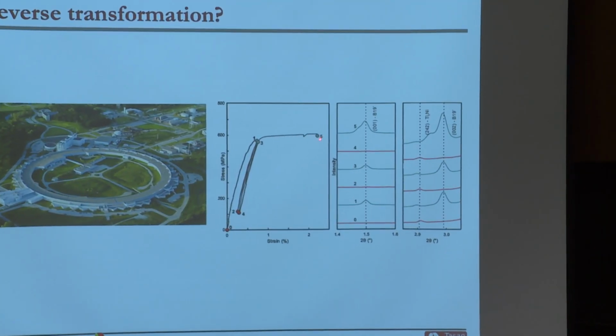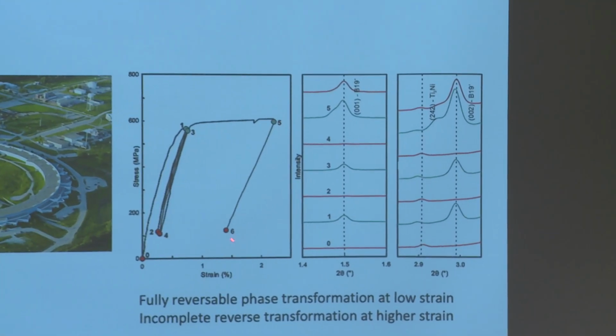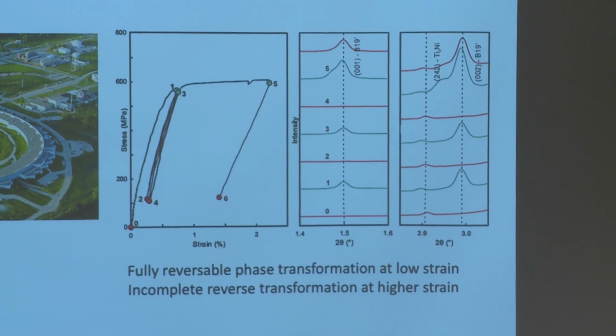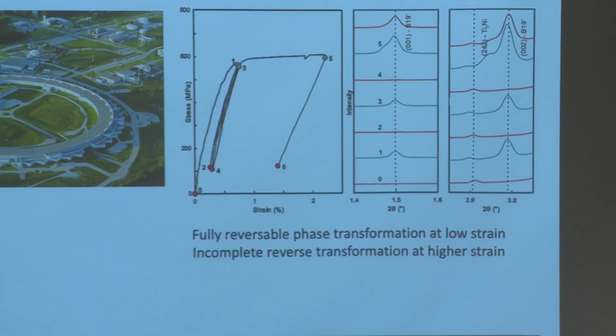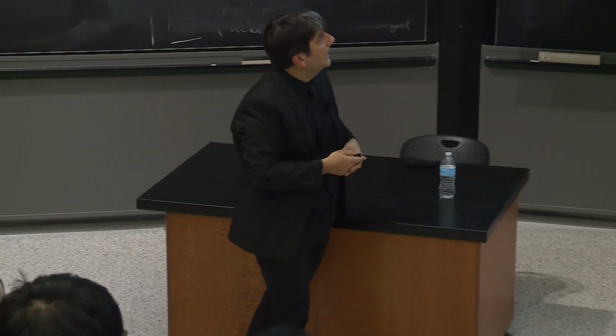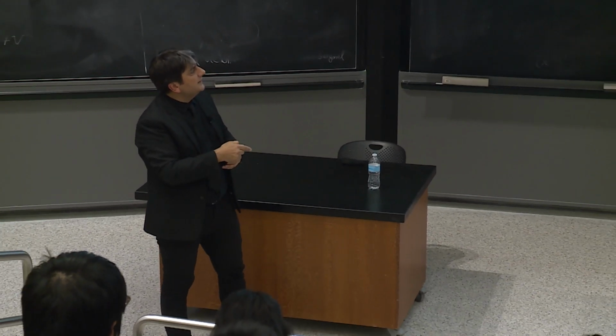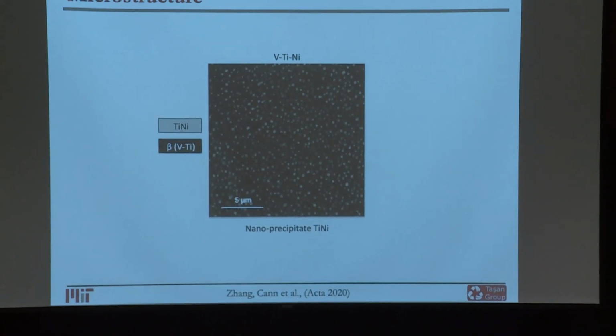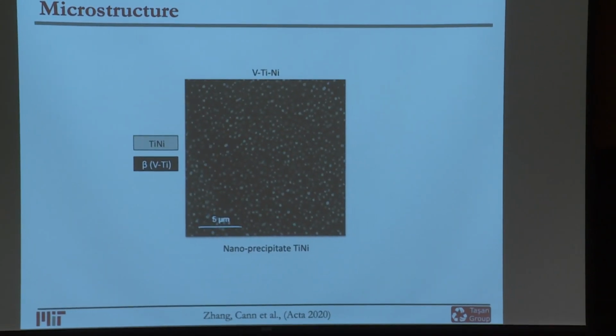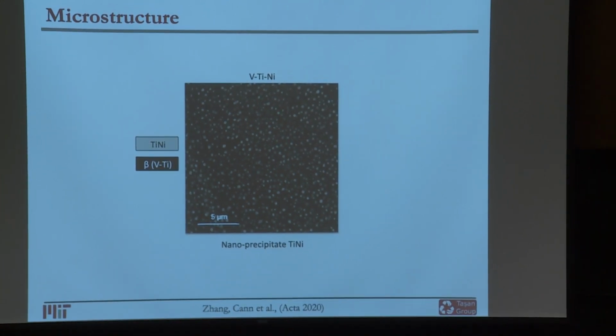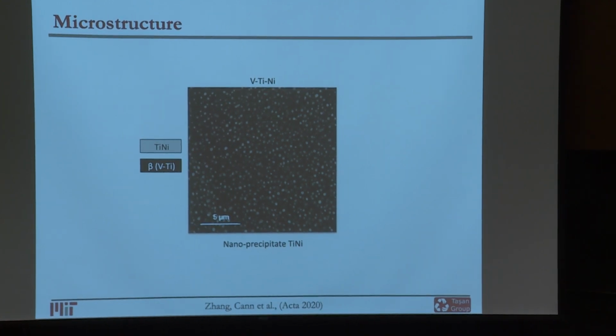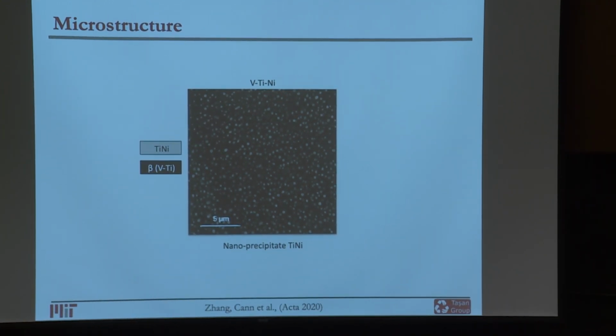So if you deform it too much, now you have the forward transformation. If you unload, it doesn't fully go back to its original state. So yes, this kind of mechanism seemed to work, but it's actually only a certain deformation regime where it sort of works. And I'm also a little bit cheating here, because the sample that we've taken to this facility doesn't only have the small titanium nickel features, but also has coarser titanium nickel features.